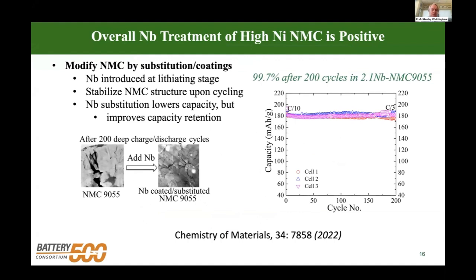So the key thing we found out, why does this work? What we found out is putting the niobium into the material stabilizes the lattice. And you can see in this image down here, no niobium, large cracking of the meatballs, a little bit of niobium, they're all minor cracks in here.